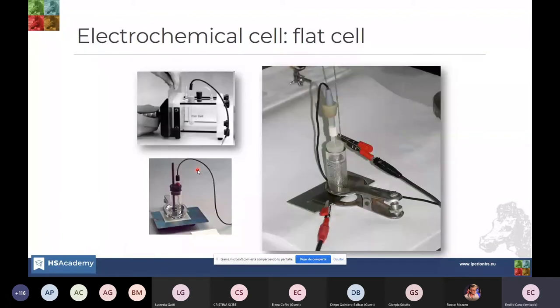So another type of cell is this one. It is the so-called flat cell, in which we keep the same elements, but we arrange them in a slightly different way. In this case, our working electrode is this flat sheet, the blue one here. And what we have is this V-cell that can be placed horizontally or vertically, it doesn't really matter, in which we put the electrolyte, and it is open at this end, leaving the working electrode, our flat sample, exposed to the electrolyte. And then we put again here the counter electrode and the reference electrode.